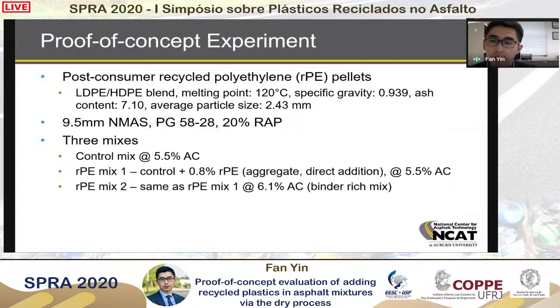When we do the mixture testing, we look at 3 different mixes: the control without the plastics, and then 2 mixes with plastic. The first one is we took the control and we are adding 0.8% plastics by weight of aggregates using the direct addition approach. And we keep the binder content the same, 5.5%. The second mix with plastic is pretty much the same as the first PE modified mix, but the only difference is that we're adding more binder to make it a binder-rich mix so that it can provide better cracking resistance and durability.